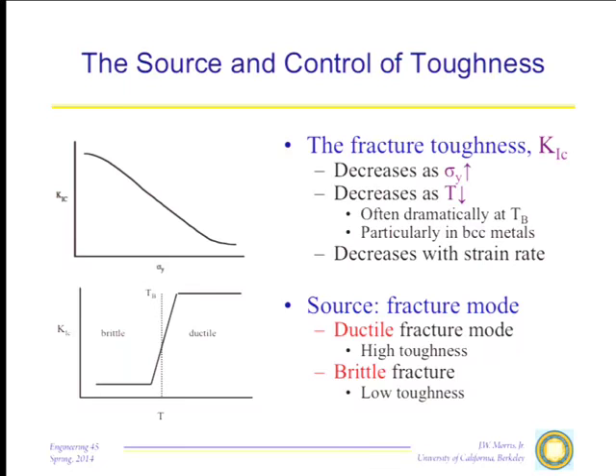For reasons that I'll tell you about more specifically later, the fracture toughness monotonically decreases as the yield strength goes up. So you can, in fact, almost always improve the fracture toughness of a material by dropping the yield strength. You lose fracture toughness when you raise the yield strength, and this is a very serious problem in structural materials because you want strength. If you don't have strength, the thing's going to fail by yielding. So you're looking for the best possible combination of strength and toughness.